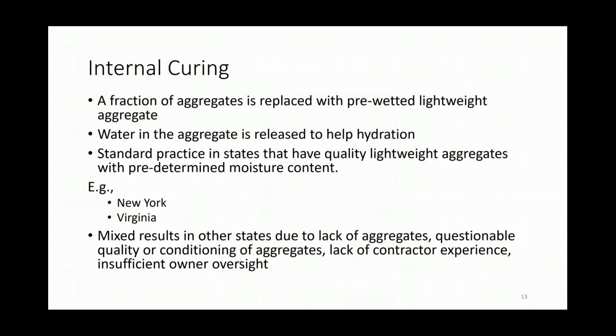All right, so we did talk about external curing, like I said. For external curing, which is wet curing like we all do, the key is to start right away. But there's this innovative way of curing concrete, which is called internal curing. Essentially, you replace a fraction of your aggregates with pre-wetted lightweight aggregates, and that water in the aggregate is released over time to help hydration. So instead of just hydrating the surface of the concrete, you're hydrating from inside out, so internally.